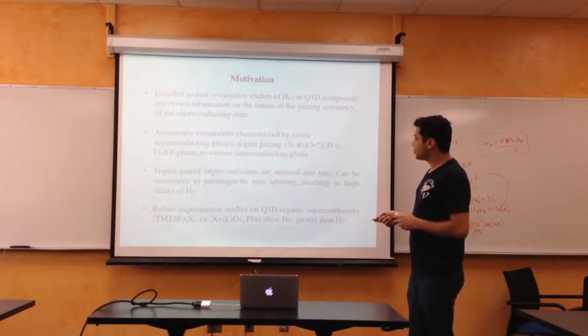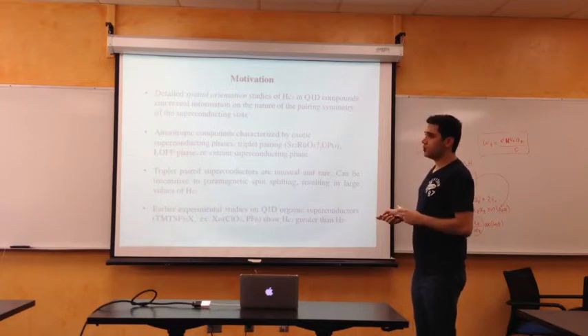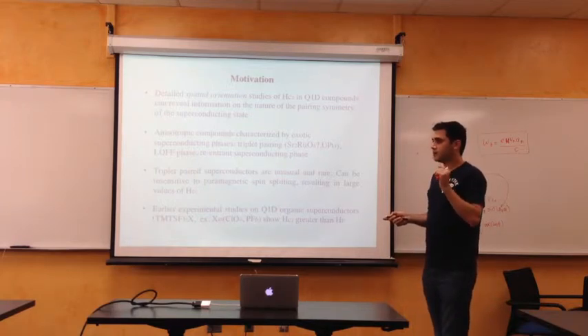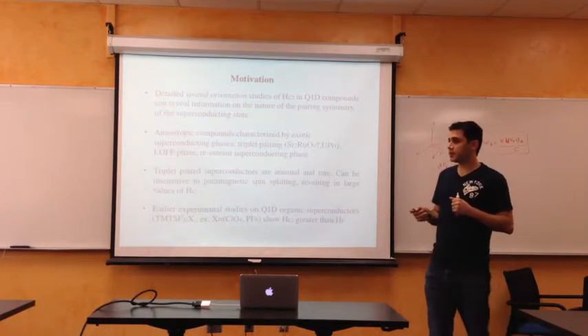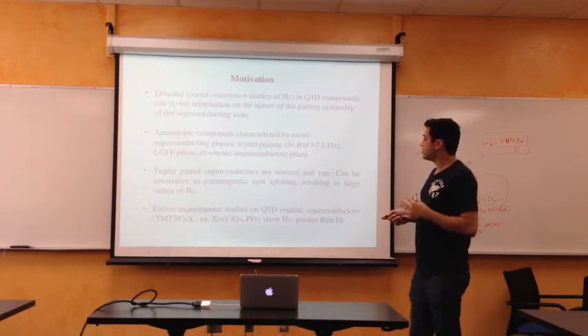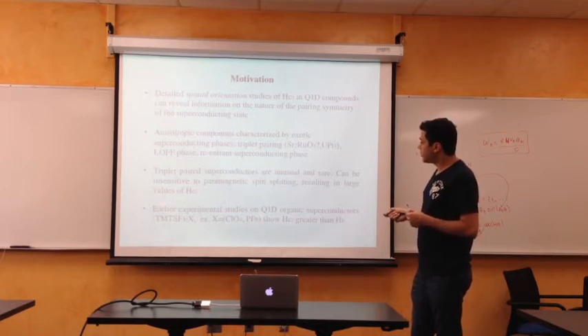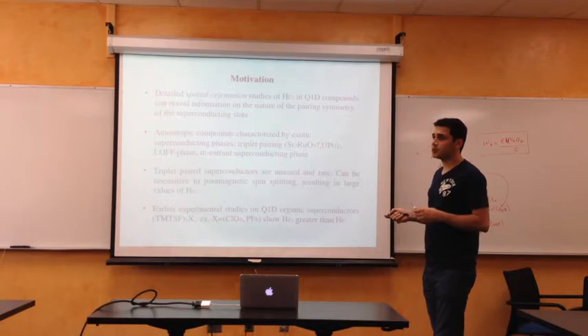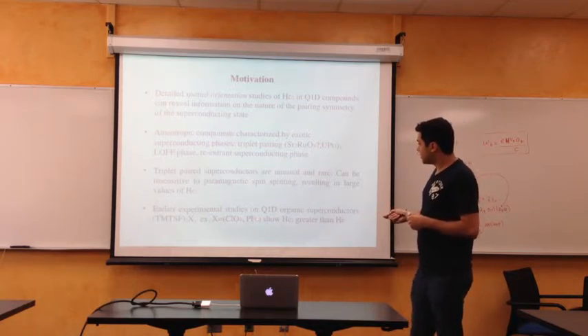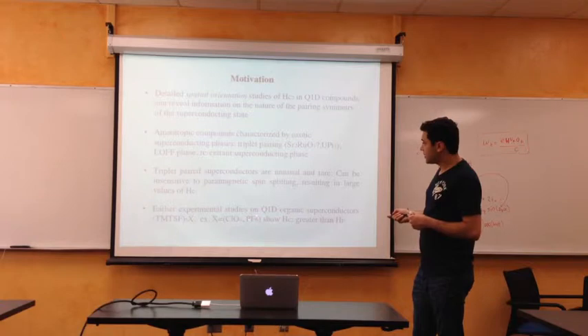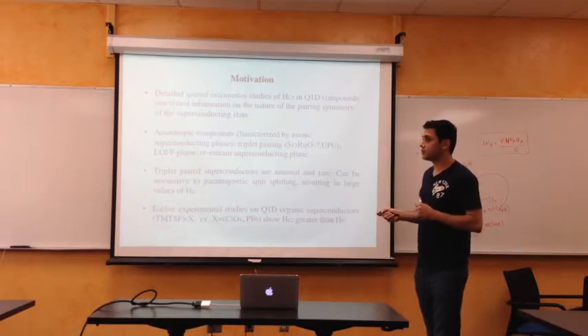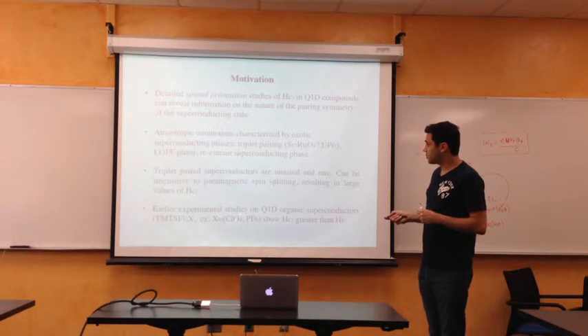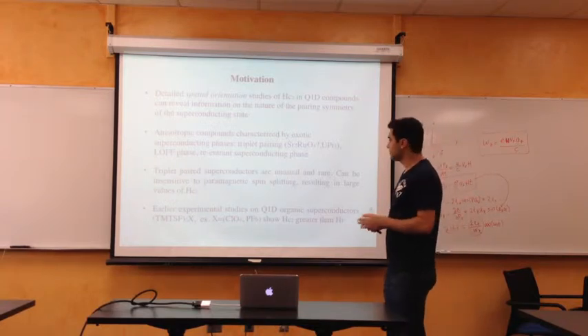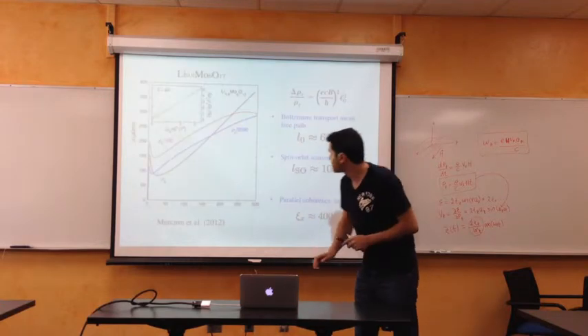Earlier studies on organic superconductors show the upper critical fields being greater than the paramagnetic field. For example, NMR measurements on PF6, an organic superconductor from the Bechgaard salt family - the NMR measurements of Knight shift showed that the PF6 case is a possibility for triplet pairing, while ClO4 is actually a spin singlet. So there's a lot of stuff going on there.